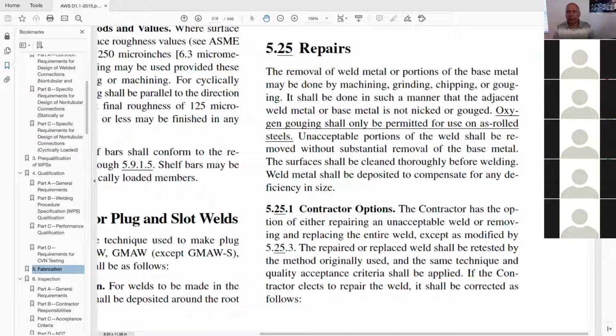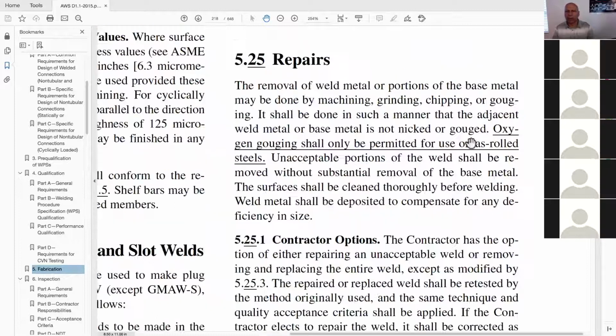Now, we've got to keep in mind that under repairs in clause 5, it says that the removal of any weld metal or portion of the base metal may be done by machining, grinding, chipping, or gouging. It shall be done in such manner that adjacent weld metal or base metal is not nicked or gouged. So for that reason, when we qualify welders, if the welder got a little carried away, careless, and took the grinder for a walk in the woods, then he nicked or gouged the test coupon outside the weld area where he was going to weld over it, then he or she is disqualified. And so we're pretty picky about that.